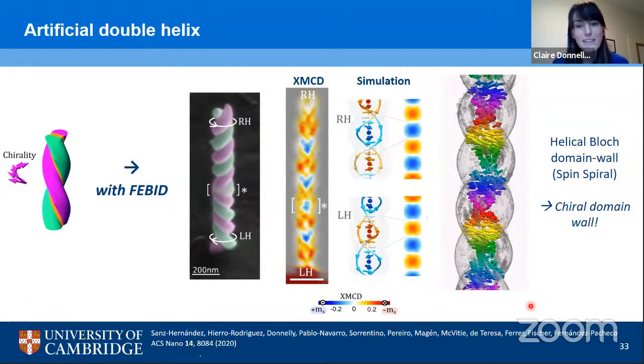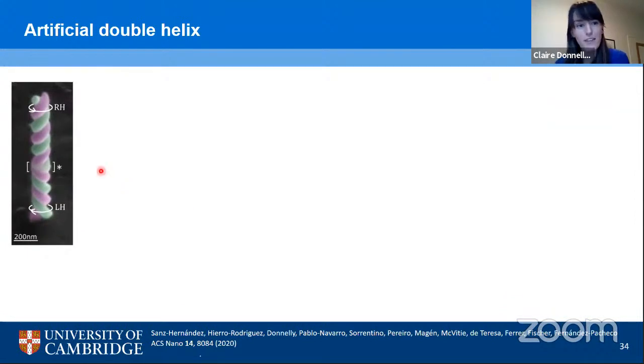But it's not just the formation of chiral spin textures that this new 3D printing technique gives us access to. If you look more closely at this SEM image, you may have noticed that there's something else going on. We are actually able to grow two chiralities within the same structure. In the bottom half of our helix, we have a left-handed chirality. The top half, we have a right-handed chirality. And in between, we have this threshold, this region where the two chiralities meet. And this is, I think, a really massive advantage of these 3D printing techniques, that we can really tailor and control the chirality spatially within our structure.